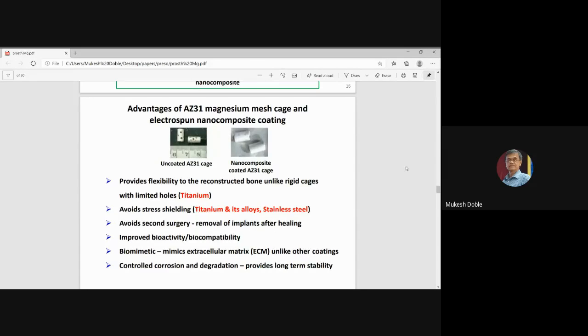Okay, avoid stress shielding, because titanium and its alloys have much higher tensile strength than magnesium. Sorry, the magnesium and its alloys have lower tensile strength when compared to titanium. So we don't have to remove it. And magnesium, as I've been telling, is bioresorbable. So in the long run, as the bone starts healing and growing, the magnesium will completely get resorbed. Bioactivity and biocompatibility are improved because we have the polycaprolactone HA. And again, we are mimicking the ECM, extracellular matrix, so we call it biomimetic.